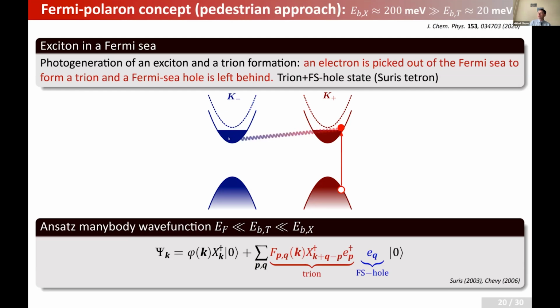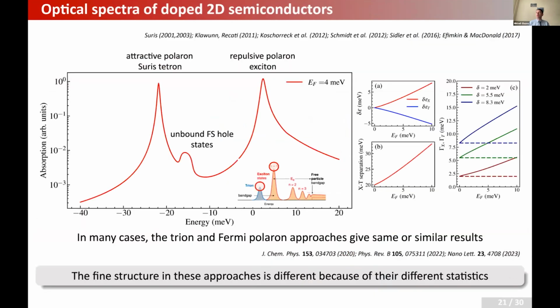Now you take into account this Coulomb interaction, and because of this Coulomb interaction, you create an electron-hole pair in the Fermi sea, something like this. And now you have a situation which can be described as a superposition of the exciton and the exciton plus an electron-hole pair in the Fermi sea. Or you can rewrite this wave function in a little bit different way. You can consider this exciton plus electron as a trion, and then you have also a Fermi sea. Very simple, so you can see, okay, it's almost like a trion. There is some correlation with the Fermi sea. And indeed, if you discuss many of the phenomena, like shuffling of the oscillator strengths between exciton and trion, if you discuss photoluminescence, even if you discuss transport properties, these both models give basically the same result. Sometimes numbers slightly differ, but it is not a strong difference.